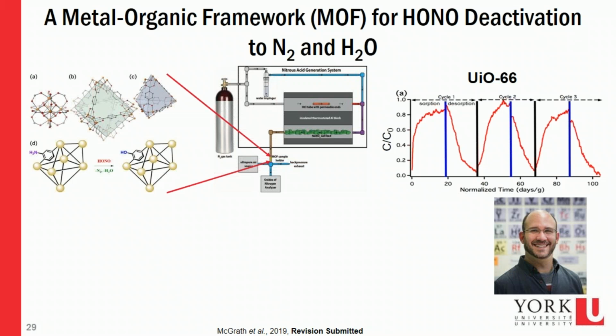So you have huge porosity within these. I'll refer you to the paper. Hopefully it'll be through review soon. The revision was just put in, it should be done in the near future. They have huge surface areas internally that you could just sorb gases onto, but if you do chemistry, you can actually come up with a much better solution. And so the chemistry that we got into looks to convert HONO to N2 and water. And we've been able to show that we can do this within a metal organic framework.